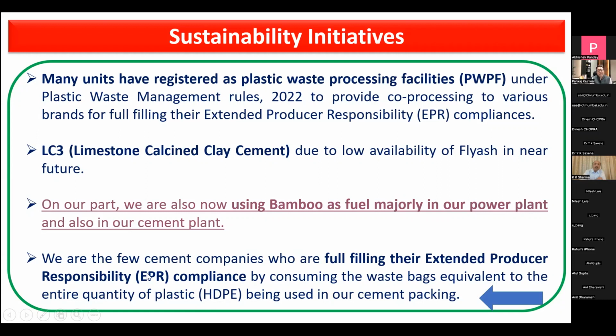Along with this, there is now calcined clay cement which this industry is looking at. Because if you see, fly ash currently is difficult to dispose of. But over the long term, the growth of thermal power plants is now reducing, and people are moving to greener sources like solar or wind. So eventually we feel that fly ash itself will become a shortage for the cement industry. To take care of that, we are now developing the LC3 cement, as it is called, where we are using calcined clay. This calcined clay is also available amply in various parts of the country. So this is also a greener initiative, which will help us mitigate the shortage of fly ash in the near future.